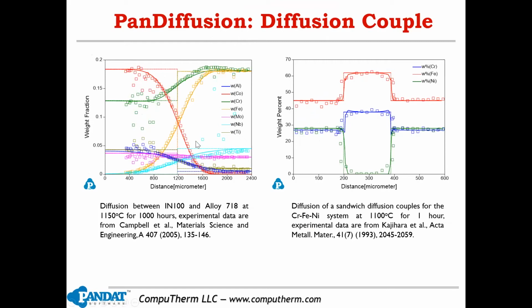The diffusion module is used to understand diffusion kinetics, such as elemental diffusion. And in this case, this is diffusion between Inconel 100 and alloy 718. Both are multi-component systems. As you can see, we can simulate how the elements diffuse into each other. And we can also do diffusion in a diffusion sandwich, like the right figure shows, okay?